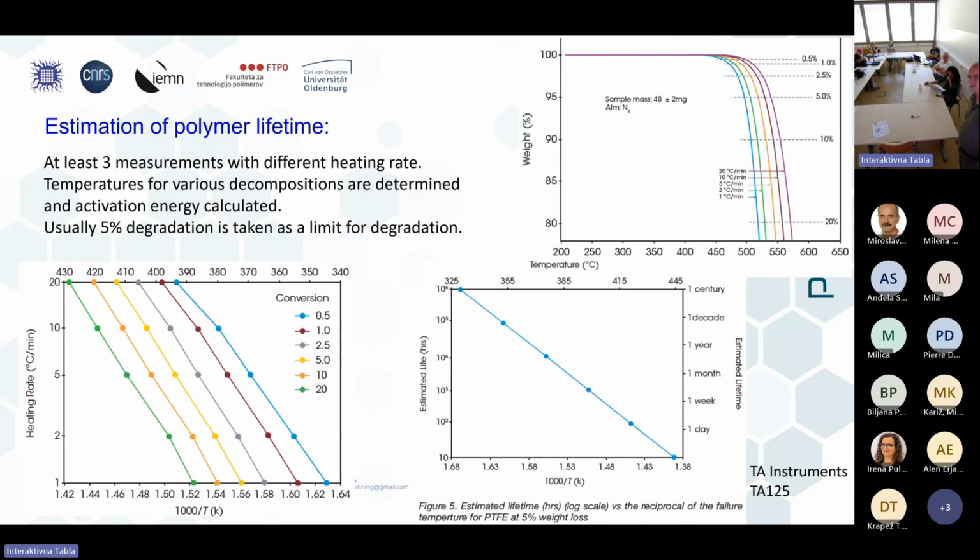So at 325 degrees Celsius, this will last, let's say, for at least 10 to the 6 hours. If we use it at a higher temperature, this will drop much more. And we can estimate that maybe this part at 100 degrees will survive 10 years or 15 years or something.